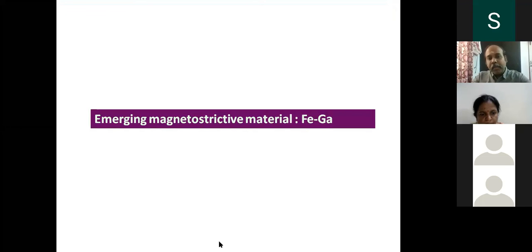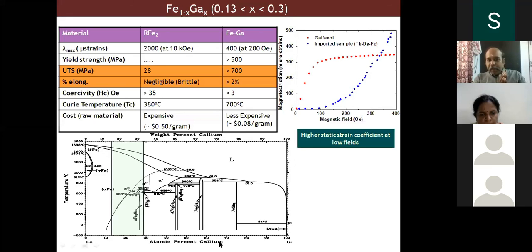So this iron gallium based alloys material program also has been taken up. When I compare this iron gallium alloy with the conventional RFe2 alloys, the magnetostriction it shows is only 400, but the only difference is it shows 2000 microstrains at 10 kilo oersteds, but it shows only at 200 oersteds. You see the graph, whatever you want is being generated at very low fields.